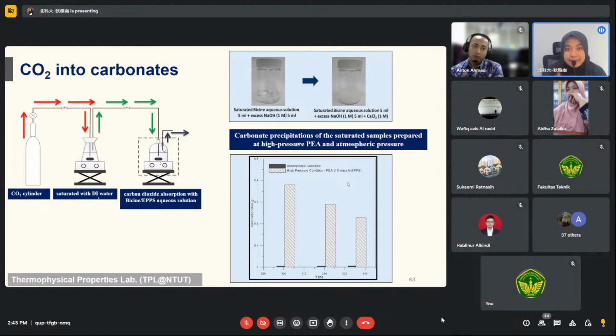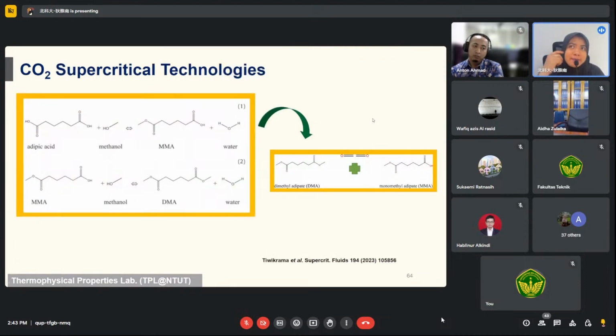So we can take the sample out and add the sodium hydroxide and the calcium chloride to see how much CaCO3 they can form. So this comparison proves that high pressure is, of course, one of the highly possible ways to capture the CO2. Actually, basically, we never capture CO2 at low pressure.